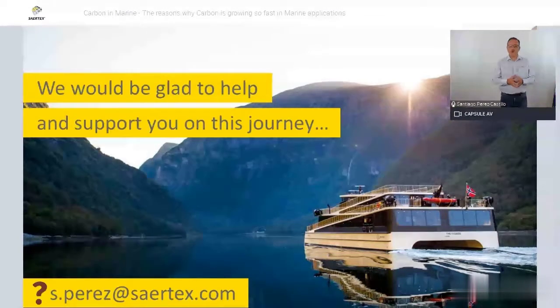Do you use glass non-wovens in combination with the gel coat? Well, glass non-wovens is used in particular cases, of course, the typical chop strand mat as a protection or as a surface finish, which you would like to have very, very glossy. But what we see is by using these special technologies, typical situations, as we mentioned before, related to the sagging, the necking, and the quilting effect are minimized and are reduced. So in most of the cases, the amount of surface protection, like the chop strand mat, is not required so much as it was in the past. Of course, in some cases, it is advisable.